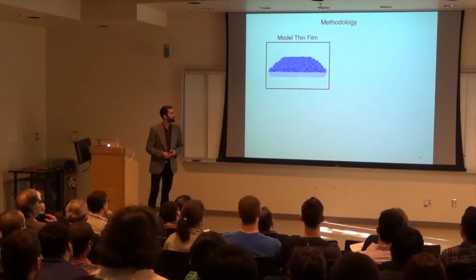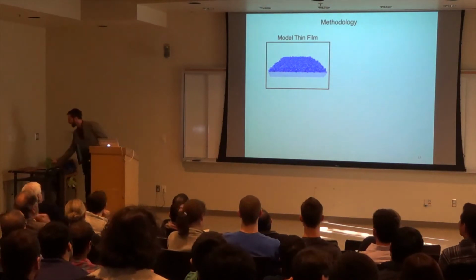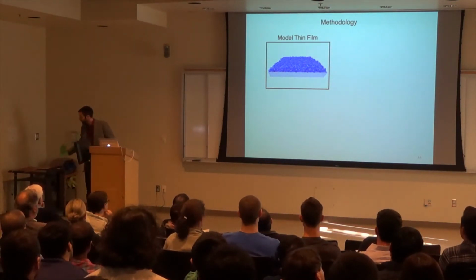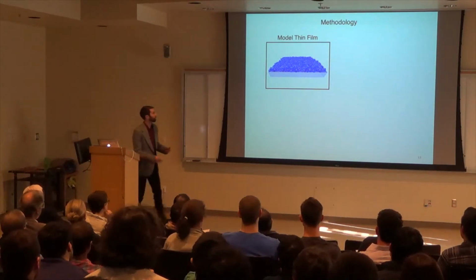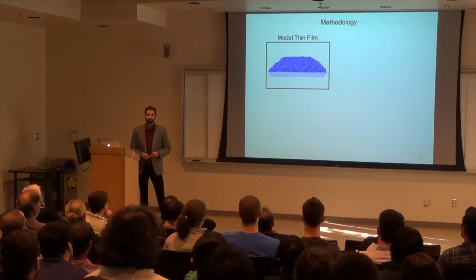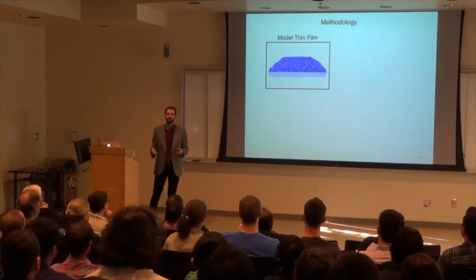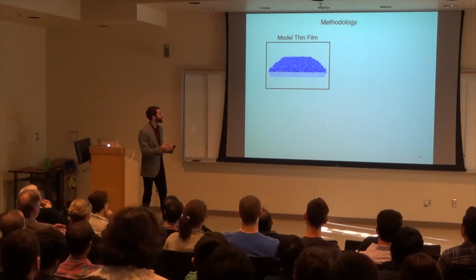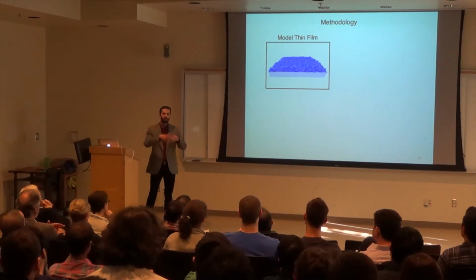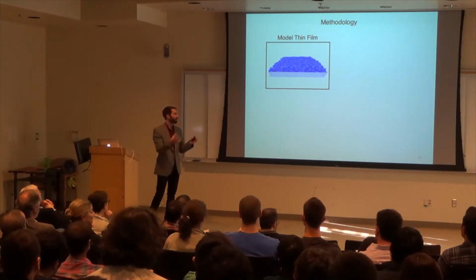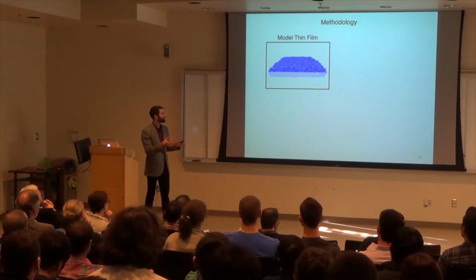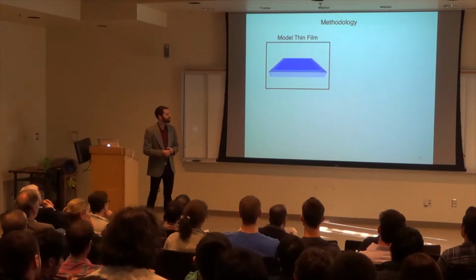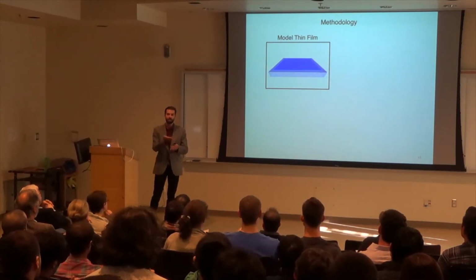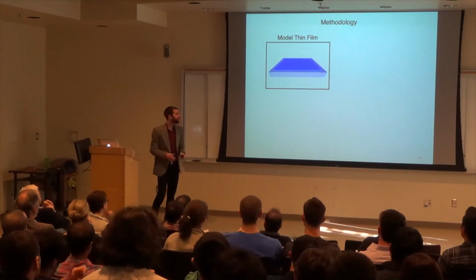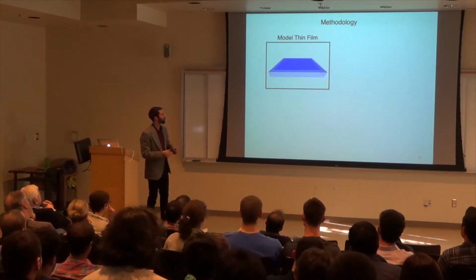And to do this, I'm going to use certain types of methodology. What I mentioned is that a lot of people study these films in a porous orientation, but these inherently convolute results because they are also high surface area. They have multiple surfaces that are exposed, and some people have issues like cracking and whatnot. So what we are studying right now is a thin film model system. We have well-defined orientations. We only have to study one surface. So that's what I'm going to reference going forward.